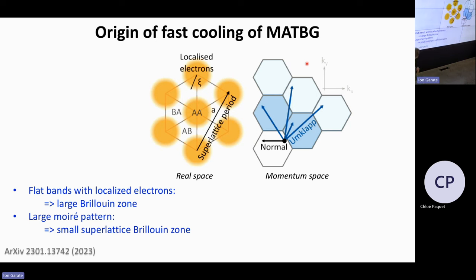And what's happening here is that, of course, you have two Brillouin zones. So you have the very large Brillouin zone associated with the flat bands, because they, of course, have these localized electrons because of the flat band, very high mass, so they're not moving anywhere. So very large Brillouin zone. On top of that, you have this quite large superlattice period in real space. So that's this picture.